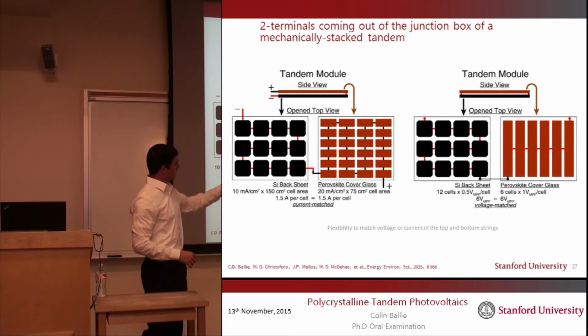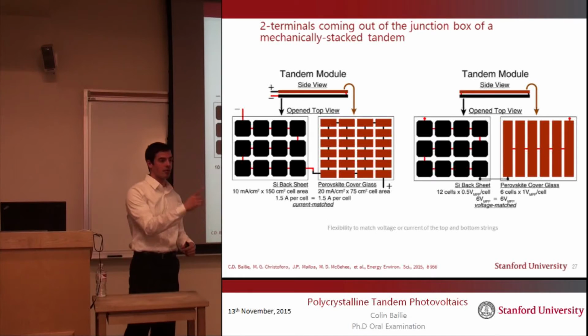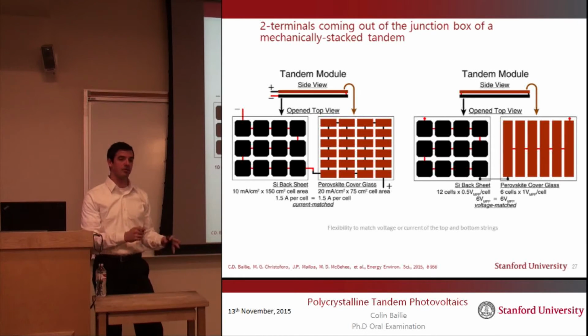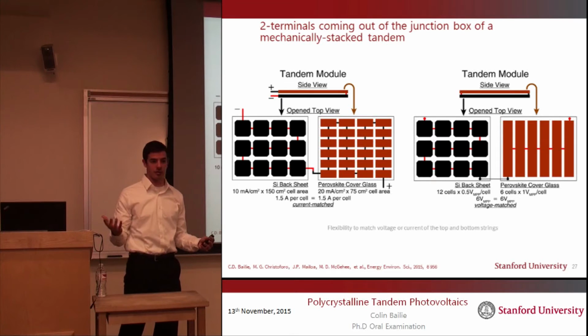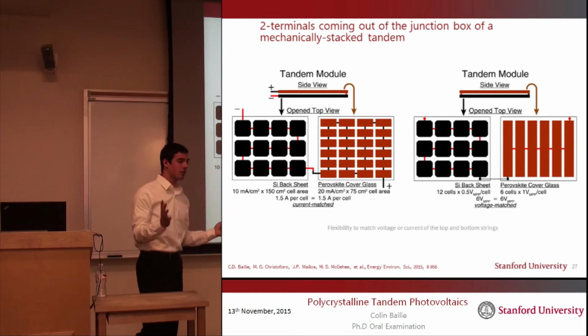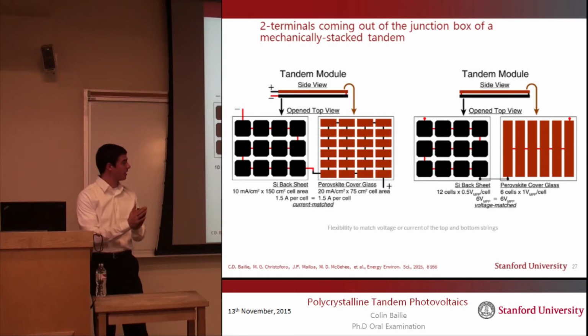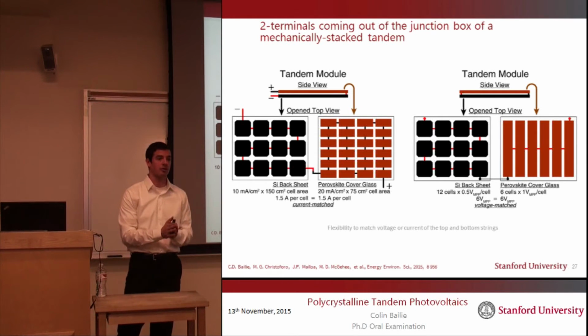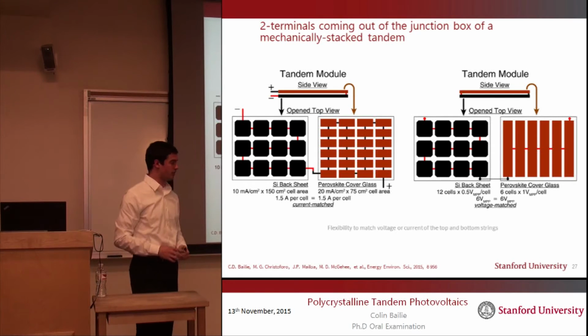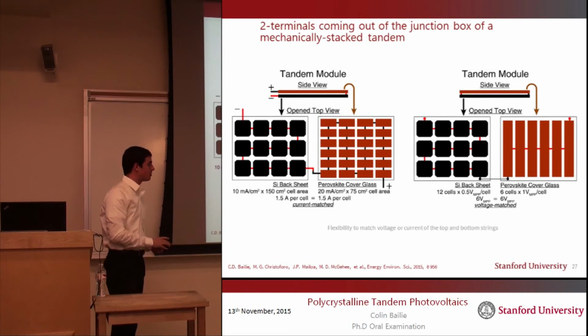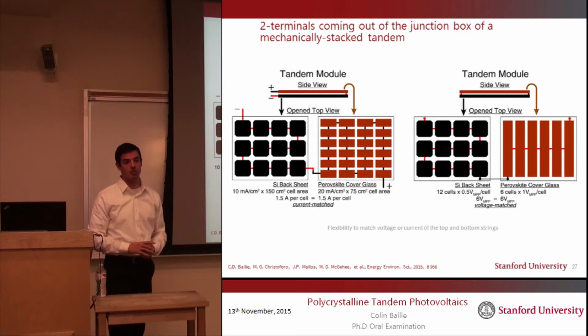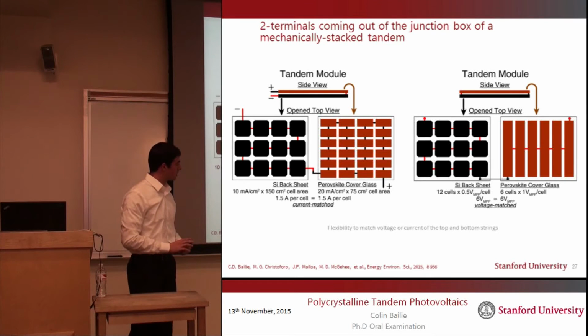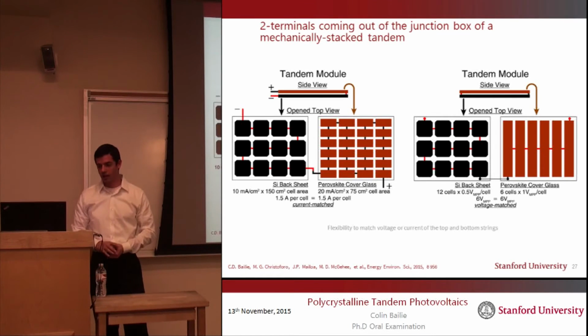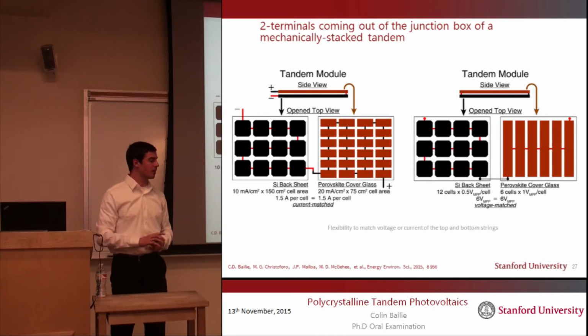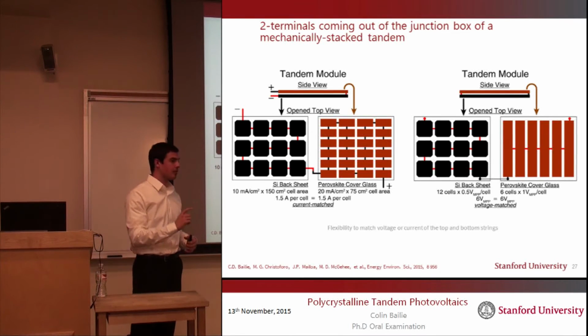So another option is to string together all of your silicon solar cells in series and separately string together all of your perovskite solar cells in series. And then when you go to put the module together, you hook those up in parallel, which means now you're voltage matched between the two. And this voltage matching is much less sensitive to the shape of the solar spectrum, and so you get less losses here than you would with the current matching. But now you've introduced some voltage matching requirements, and these are sensitive to temperature.